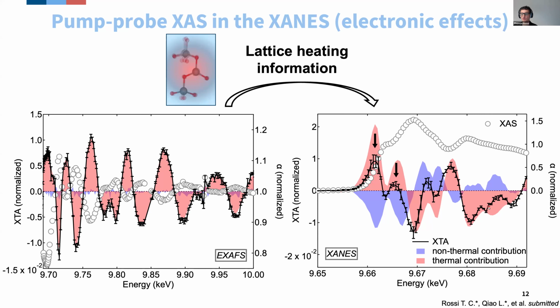And the difference between these two curves is what is highlighted in blue. And this is what we call a non-thermal contribution to the XANES. We can discuss maybe later on what is the validity of splitting the pump probe signal into different contributions, but this is essentially how we analyze it. And it turns out that this non-thermal contribution is the electronic information that we are looking for. And the only way to access it is by first doing this work of trying to isolate what are the thermal contributions to the pump probe data first.